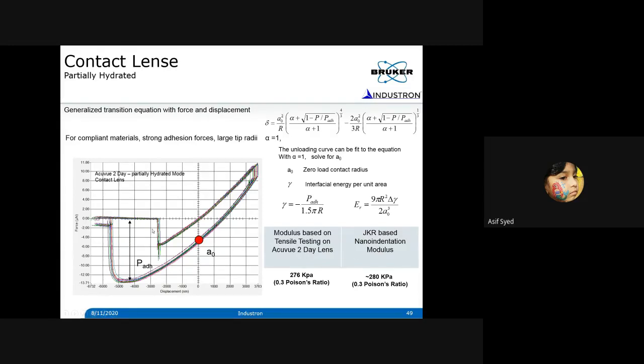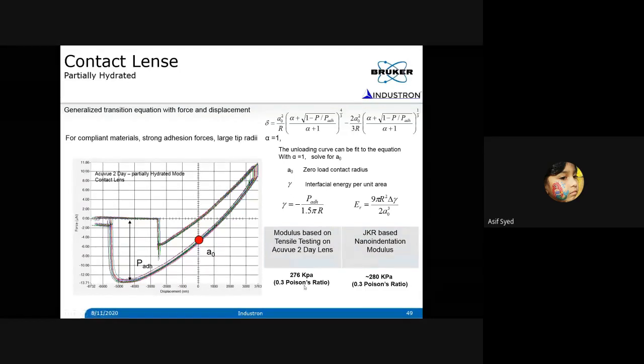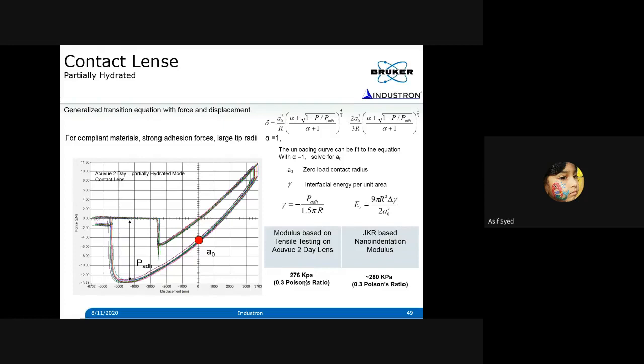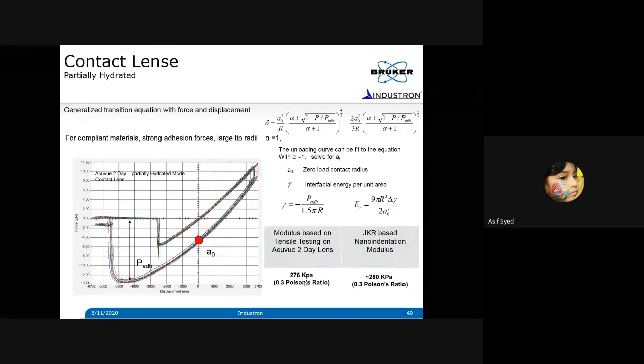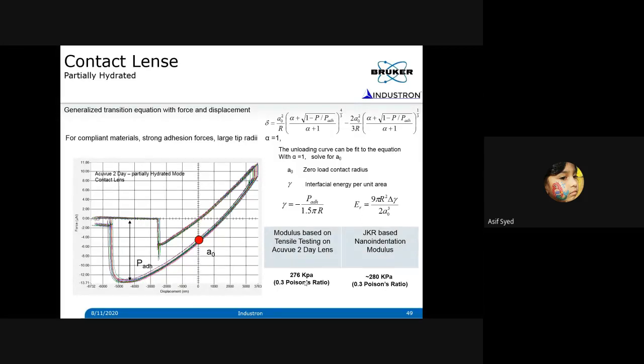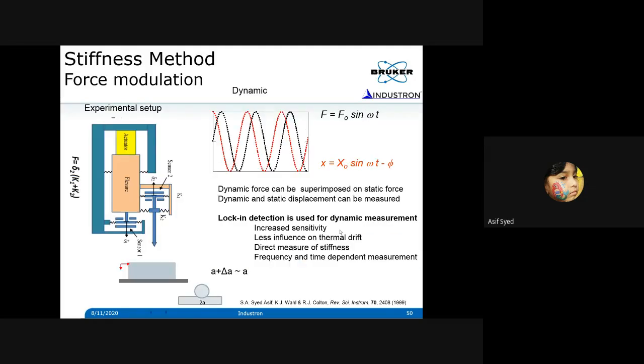When we did that on this contact lens, and compared it with the modulus measured by Johnson & Johnson using their tensile testing, you can see the agreement between these two. This is exactly the condition that they use for FDA approval, because the FDA mentions this is how you have to measure the modulus. When they tried to measure it with the indentation-based technique, it didn't match the number they were getting with the tensile testing. But when we did it with this method, with the modeling approach, the modulus matched pretty close to what we expected from the tensile testing measurement. So they are trying to figure this out with the FDA to get this kind of material testing technique approved.